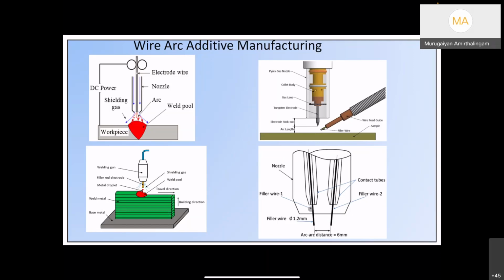In most cases, we use a dual wire, to achieve even higher productivity and functionalize the compositions as and when we build layer by layer. So the main learning you can take is that wire arc additive manufacturing uses a simple welding torch to build layer by layer, so that components can be fabricated using wire as a feedstock. As in the case of gas metal arc welding, the wire itself melts, and it also acts as an electrode. In gas tungsten arc welding, we add external filler, and then that melts and gets deposited.